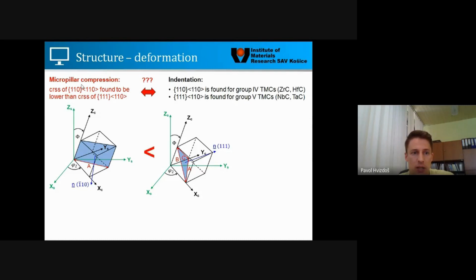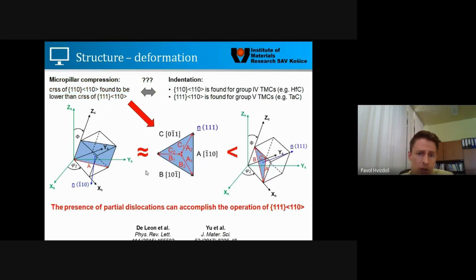So here is what we got. In the case of micropillar compression, we found 110 to be lower than the 111 type. However, in the case of indentation from the literature, we got slightly different results, because, as I just mentioned before, the 110 was known for group 4 transition metals, but for group 5 transition metals the 111 was the dominant one. To explain this, we had to check additional things, which is the presence of partial dislocations. There are cases when partial dislocations can be formed, which makes possible the activation of the 111 plane.